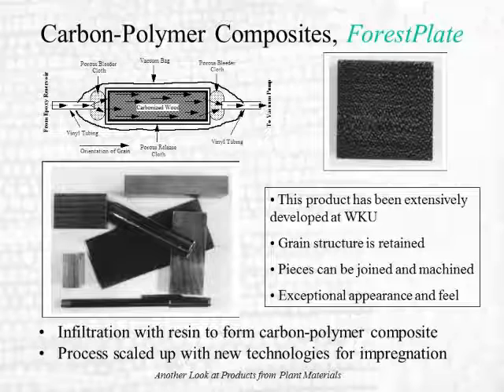That resin then solidifies or cross-links to leave you with a 2-phase material. In the case of the samples going around, they're in epoxy and carbon composite. And you see all the grain features in that sample. You do it to a variety of different sizes, and you can machine it and shape it.